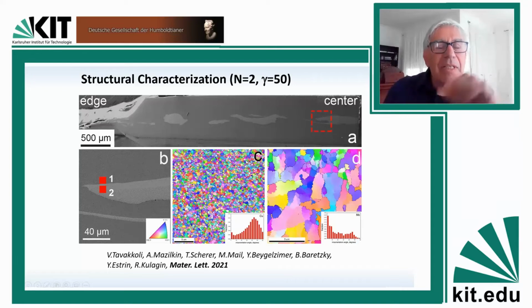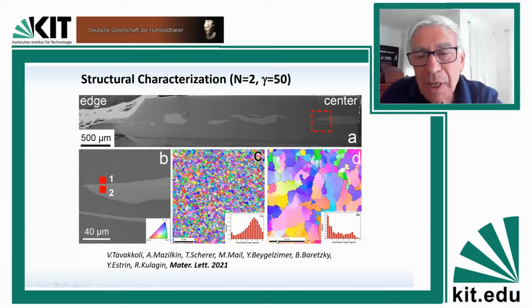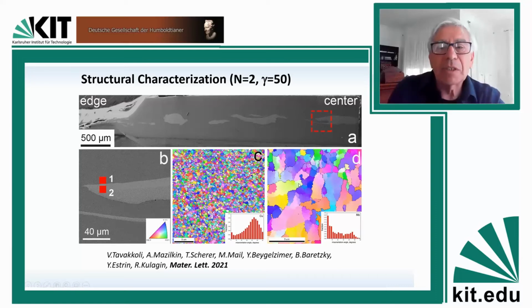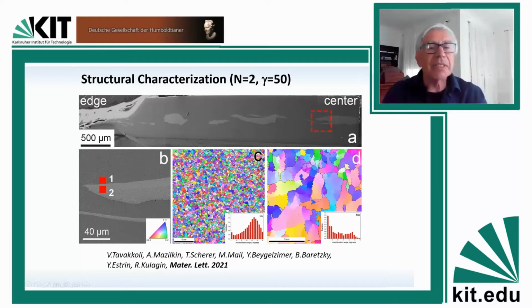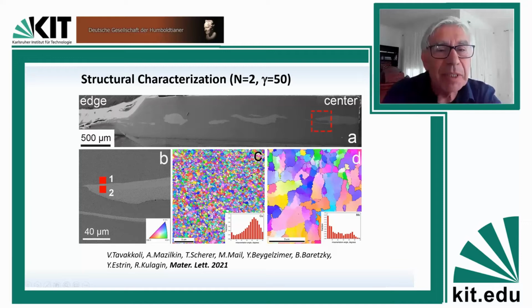You will recognize immediately that copper has the sub-micron grain size. The average grain size is sub-micron. Here the scale bar is 5 micrometers. Here it's 3 micrometers. So the molybdenum has the grain size in the micrometer range, copper in the sub-micrometer range, meaning that its mechanical properties are very good. It's very strong.